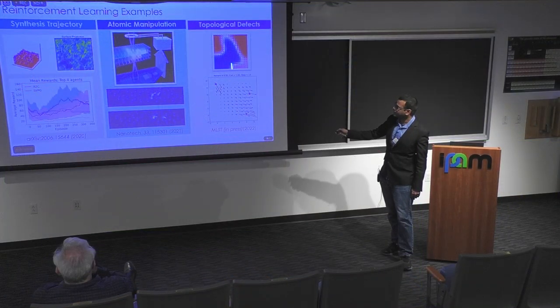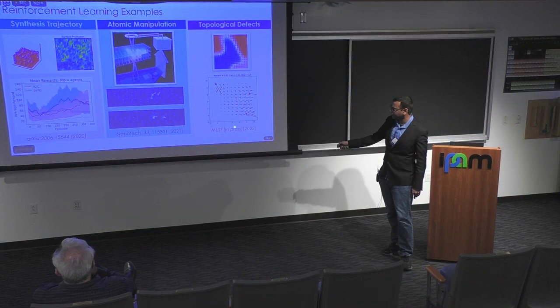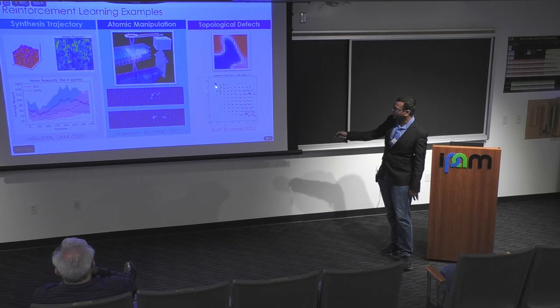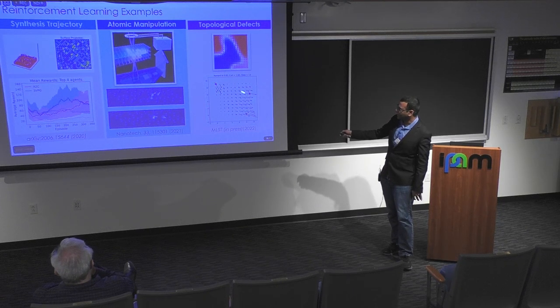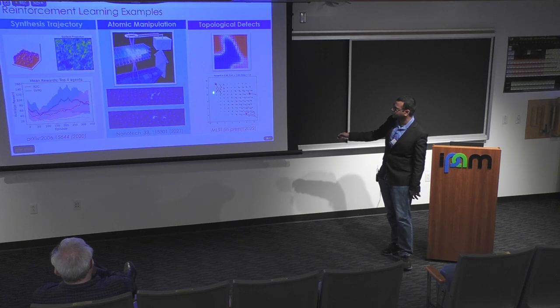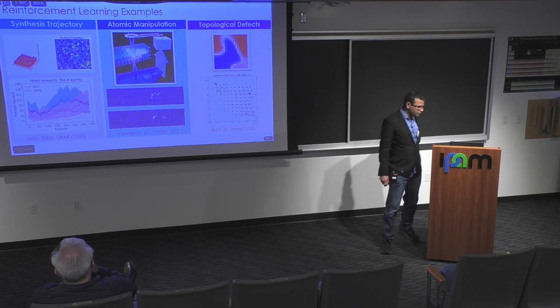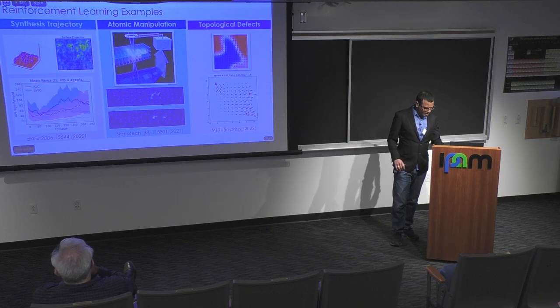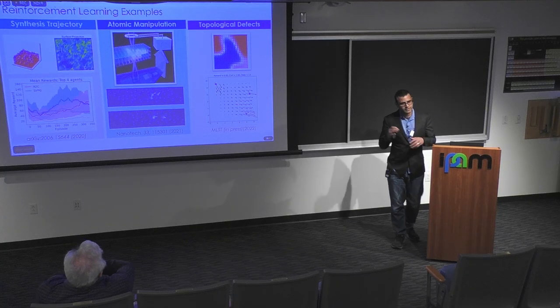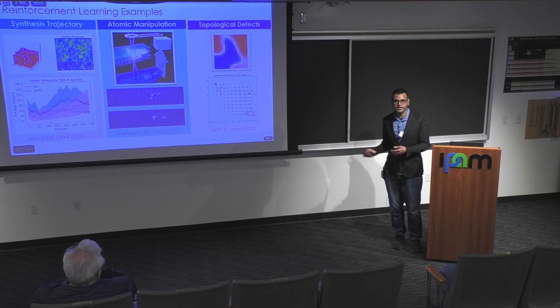And then very recently, this was just published, it's actually in press now, in MLST, how we can move defects in ferroelectric materials, again, in a simulated environment, so that we can optimize things like curl of vector fields, which is very interesting from the ferroelectric standpoint. But the point here is that we created this algorithm and then we applied it to some simulated cases.